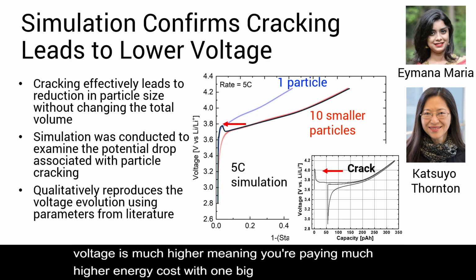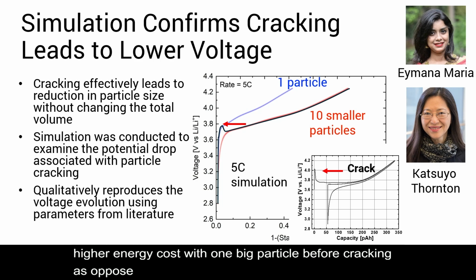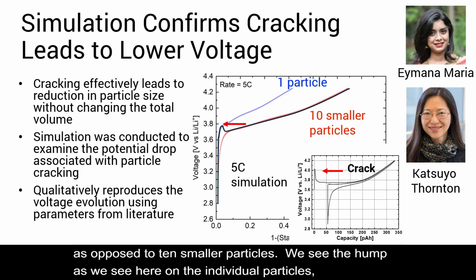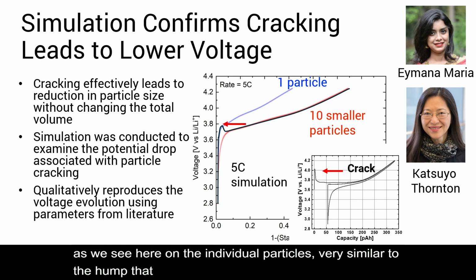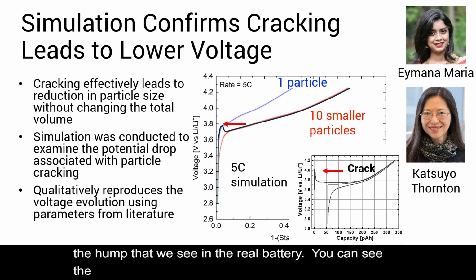And so what we think is happening is that it cracks at the very beginning, going from this 1 particle regime into the 10 smaller particle regime, and we see this hump, as we've seen here, on individual particles, very similar to the hump that we see in a real battery. You can see this magnitude is larger because we think it doesn't crack to 10 particles. It actually probably cracks to more like 100 or 1,000 smaller particles. And so this qualitatively is able to reproduce this voltage profile that I say is very significant.